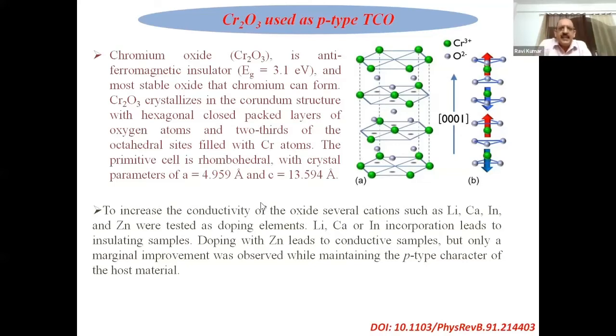And if you look at its structure, it has a corundum structure with a hexagonal close packed layer of oxygen atoms, and 2/3 of the octahedral sites filled with chromium atoms. Its primitive cell is rhombohedral with crystal parameter a equal to 4.959 angstrom, and the c axis is very large. Now, how to increase its conductivity? Various efforts were made using lithium, calcium, indium, zinc, all those kinds of things. But some of them are not giving any conductivity, or they lead to an insulator, or they are n-type, or their conductivity is very, very low.